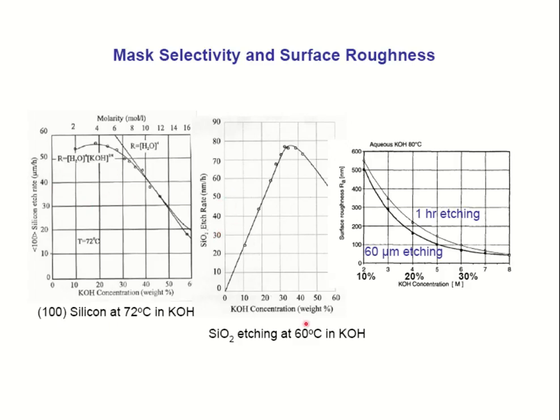So for example, let's say you're using 20% of KOH here, then the silicon dioxide etch rate is less than 50 nanometer per hour, right? In 1 hour only 50 nanometer, this is good for the masking material. But if you use 20% KOH here, the silicon etch rate is more than maybe 55 micrometer per hour, right? About 1,000 times higher for the silicon rather than the silicon dioxide. That's why silicon dioxide is good for the masking material for silicon.